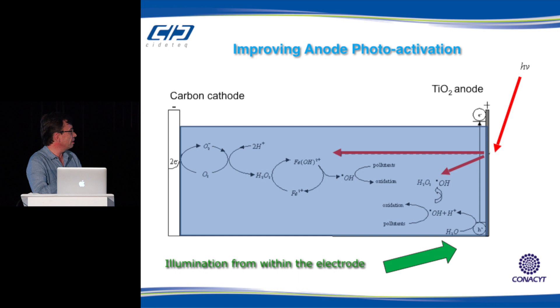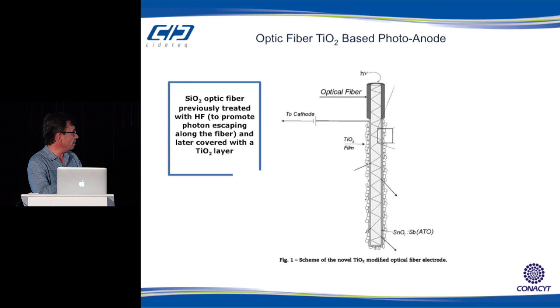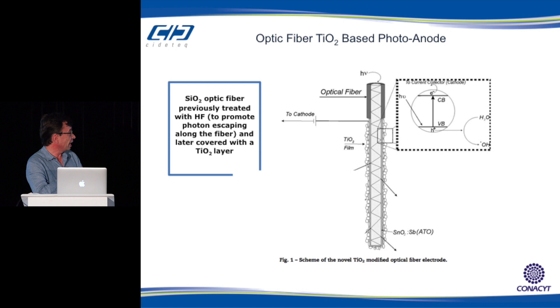With the first reactor, we found a problem: the UV light had to penetrate through the solution and the reactor walls. So we did a project using an optic fiber with a TiO₂-based photoanode. The idea was to use the optic fiber as a light hose. We treated a silicon oxide optic fiber with hydrofluoric acid to change the refraction index of the material, allowing light to escape along the fiber. We then coated it with titanium dioxide so that the TiO₂ coating could be activated from the inner part of the fiber, not from the exterior.